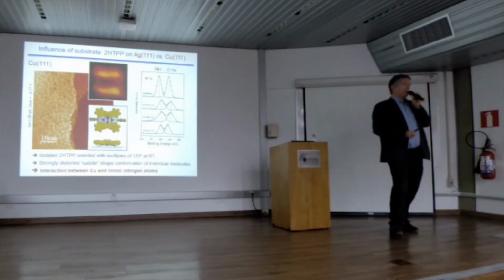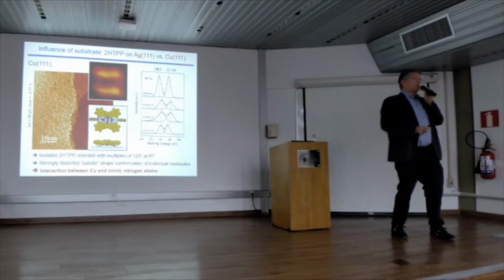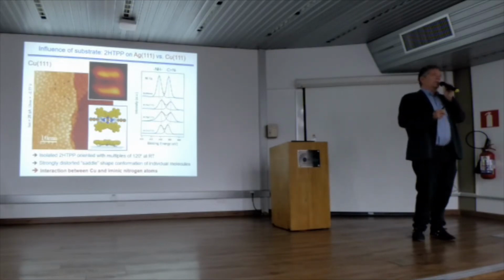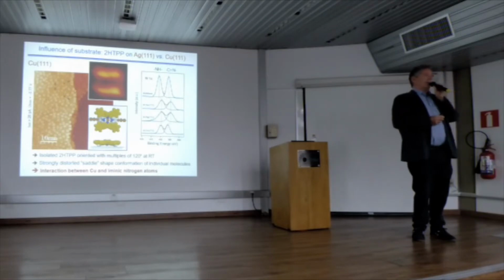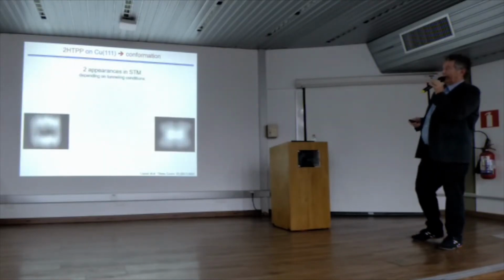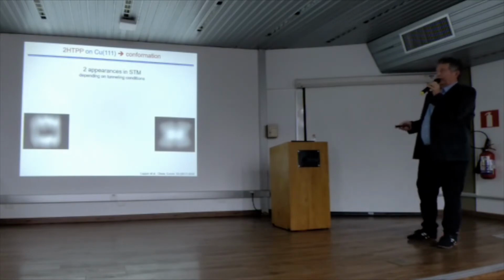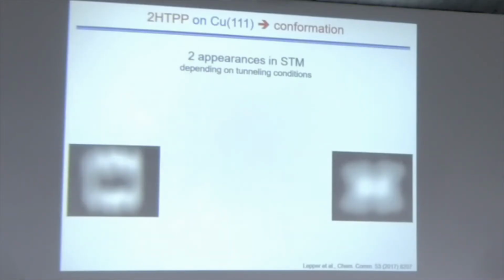Okay, now we come to a little difficult point for all people working with STM, because you don't always have what you believe to have. And here we have a very classic example. If you do STM, and the interesting thing is, after observing it ourselves, we went into literature and we also found it in other papers, that the same molecule, one sometimes looks like that, and sometimes looks like that. So here you have this longish protrusion, and here you have 2 bright protrusions. It's the same molecule, nothing happens. It's only a different tip.